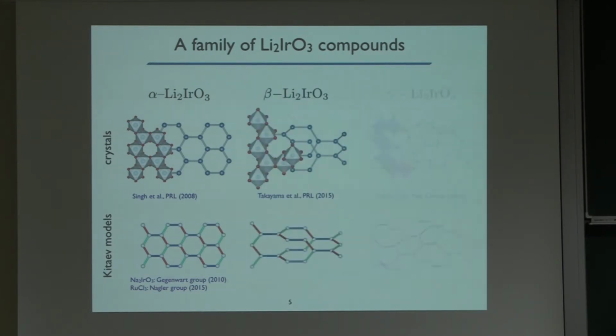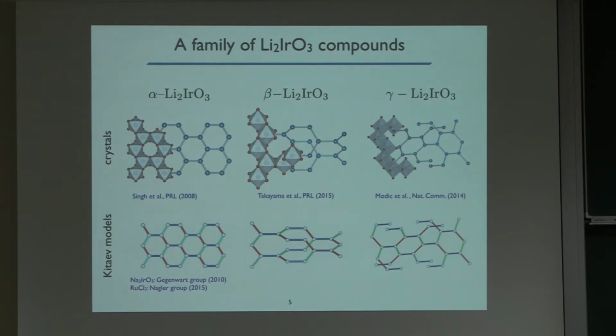Now, lithium iridates are especially interesting because you don't just get honeycomb lattices. You also have two other lattice structures you can get, and these are called beta and gamma lithium iridate. It's just a numbering scheme. And the interesting feature here is that these lattices are truly three-dimensional. They're not layered two-dimensional, but three-dimensional. And I realize these lattice structures are quite hard to look at when you see them for the first time, so let's focus on the important features.